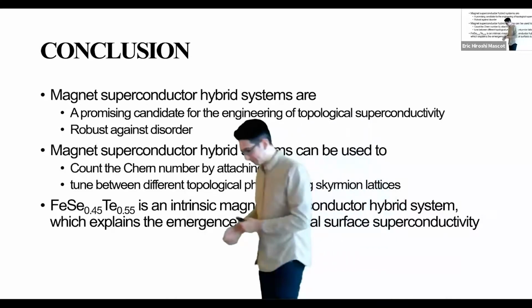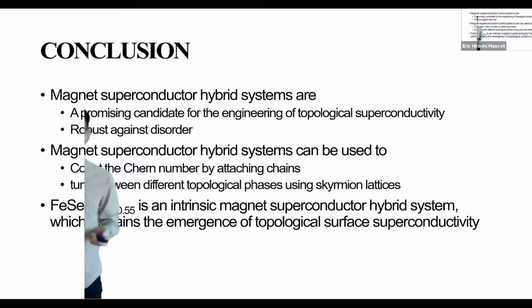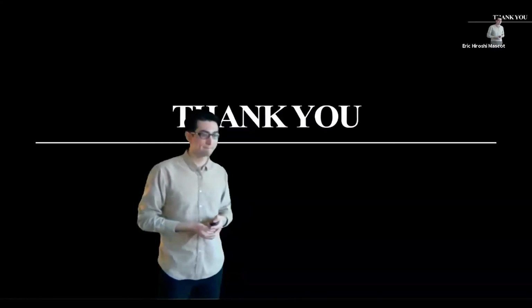So in conclusion, these magnet-superconductor hybrid systems are a promising candidate for the engineering of topological superconductivity. And these systems are very robust against disorder. And we can use these systems to manipulate Majorana zero modes and use it to count the Chern number by attaching chains. And we can tune between different topological phases using Skyrmion lattices. And lastly, FeSeTe is an intrinsic magnet-superconductor hybrid system, and this explains the emergence of topological surface superconductivity. Thank you.